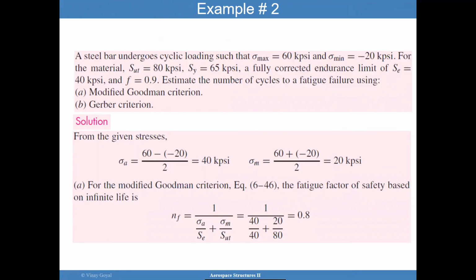So let's look at example number 2. A steel bar undergoes cyclic loading such that sigma max is 60 KSI, sigma minimum is minus 20 KSI. For this material, the ultimate tensile strength is 80 KSI, the yield is 65 KSI. And then the fully corrected, it's already been corrected for the Marin factors, the endurance limit for that is 40 KSI with an F of 0.9. We want to estimate the number of cycles to failure using the modified Goodman criterion. I won't do the Gerber criterion. I will flash it for you. You can pause it and then study that on your own.